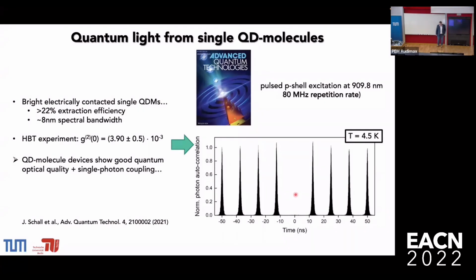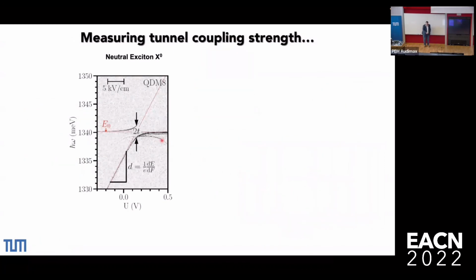So we first demonstrated that the things were good for generating quantum light. So there you see a nice paper where we demonstrated the molecule does generate quantum light, just like the single quantum dots do. We could measure the strength of the tunnel coupling. We did this for many different molecules. There you see experimental data where you see the anti-crossing from which we get the strength of the tunnel coupling.